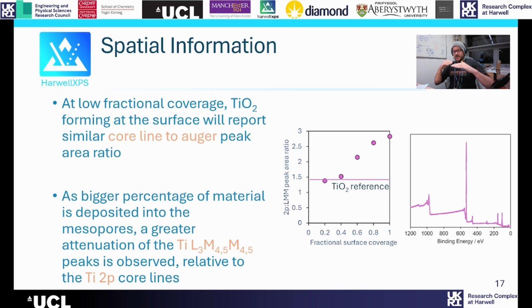When we start to add enough titanium that we're coating the pore walls as well, we're then going to start to see an imbalance, because we are going to see Ti2p signal from the inner pores. We are not going to see the titanium LMM Auger signal from inside these pores. So this peak area ratio increases because we have a difference in how we are coating the external surface versus the pore walls during our synthesis. And it seems as if there is some kind of diffusion limitation in our synthesis, so that we preferentially coat the external surface before we start coating the mesopores.